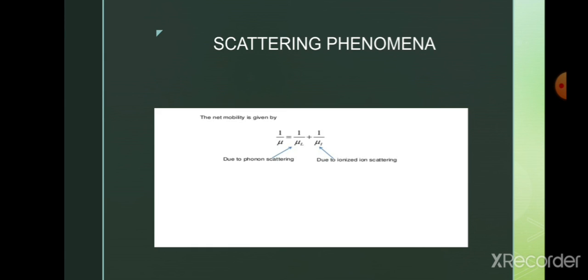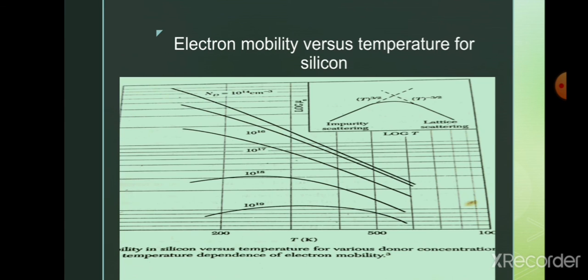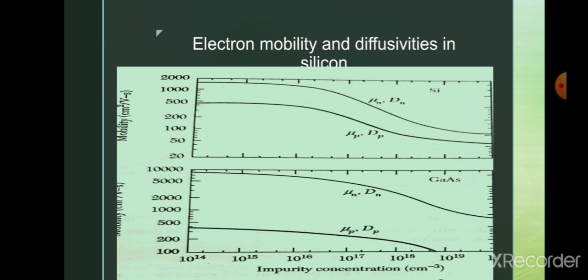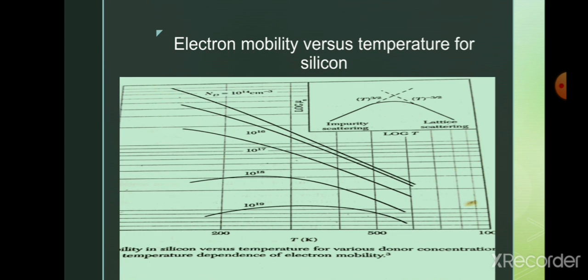The measured electron mobility as a function of temperature for silicon with 5 different donor concentrations is shown in the diagram. The theoretical temperature dependence of mobility is due to both lattice and impurity scatterings. For lightly doped samples, that is samples with doping of 10 to the power 14 per centimeter cube, the lattice scattering dominates, and the impurity scattering is most pronounced at low temperatures. The mobility increases as the temperature increases, as can be seen for a sample with doping of 10 to the power of 19 per centimeter cube. For a given temperature, the mobility decreases with increasing impurity concentration because of enhanced impurity scatterings.